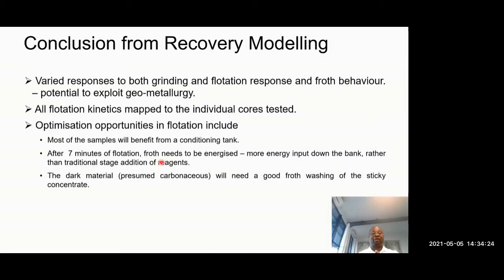But more importantly, the optimization opportunities in that particular case included this: when you watch the material and how it floats, beyond just the calculation and the rate discussion, you could actually see that typically after 7 minutes it just became very lethargic. And what we do typically is just dose more reagents in there, with more cost. But I found, and I just tested it, that if you just increase the energy a little bit, you could actually get the same amount of material. So you could have that in mind, and in a very non-normal way, make sure that in the middle of the plant the energy is not lethargic, bringing it up in combination with the air. That doesn't cost you any operating cost, and over a life of mine, you're talking lots of money. You can only see that when you scrutinize the material as it's being tested.